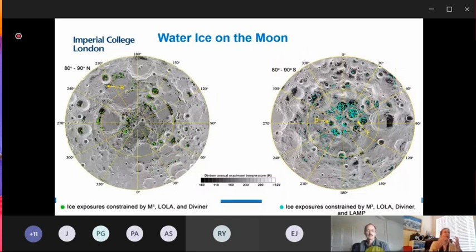People are very excited about the presence of this water ice, because if we can release the water ice that's trapped in the regolith, then we have both water and we can produce oxygen. Now, the Americans in particular are very excited about this, and they have plans to effectively go and put a giant tent over these regions. You heat it up slightly, the water ice sublimes, you can collect it, clean it up, and there you have your water.